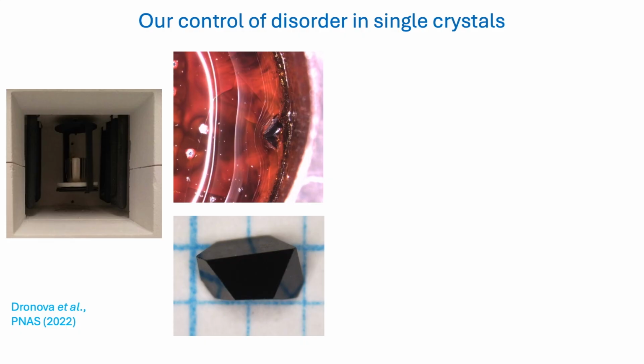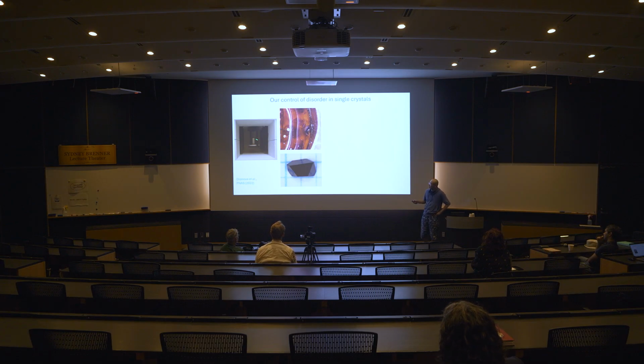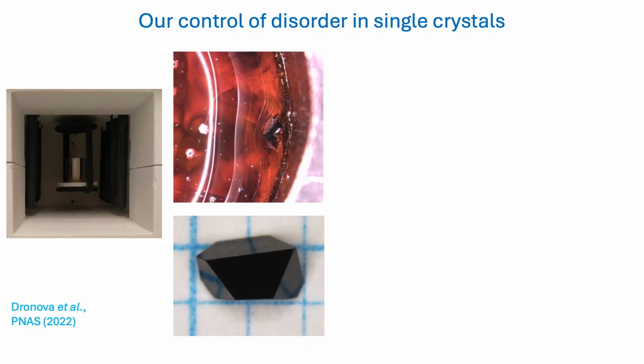So what we had started with is a so-called solution growth process. You use a platinum crucible and put your components in that with a molten, very low melting point oxide, a boron oxide, part of the boron oxide family. Then you basically heat up to 1,000 Celsius-ish, and then you cool down slowly. You can see crystals develop on the wall of the platinum crucible. And if you grow it cleanly, you can get a very beautiful-looking crystal with very flat facets.